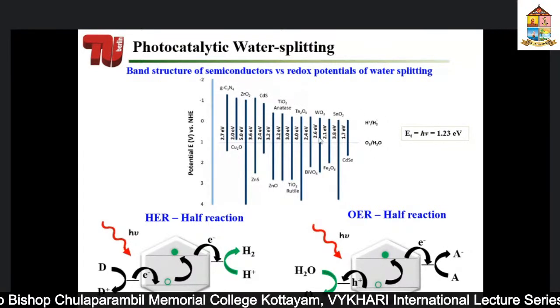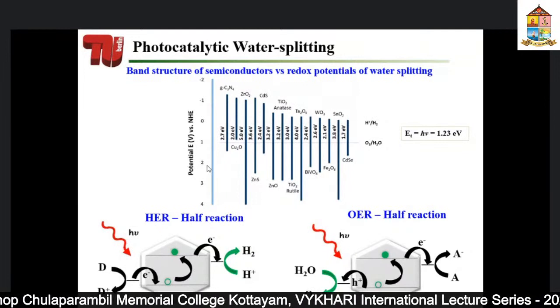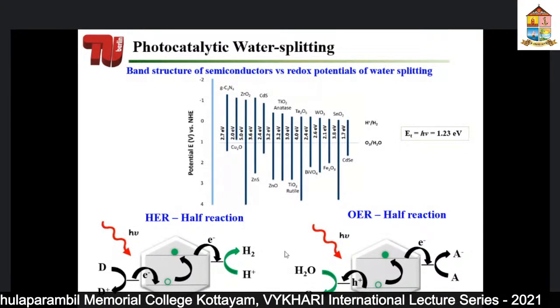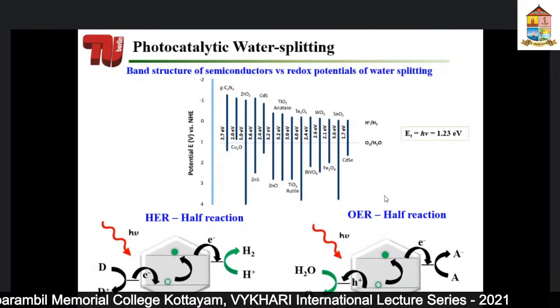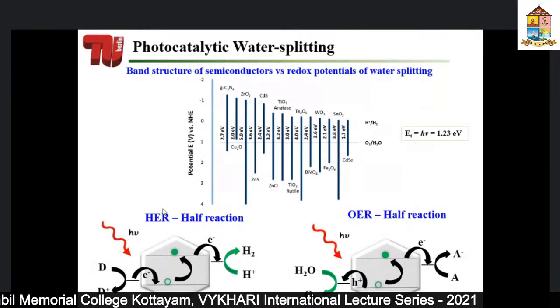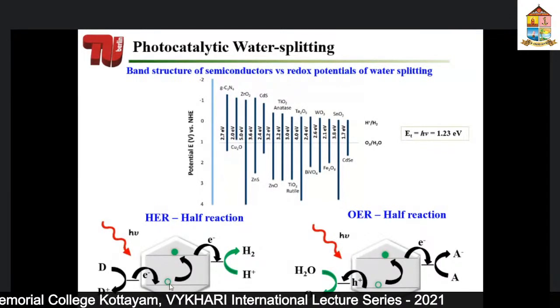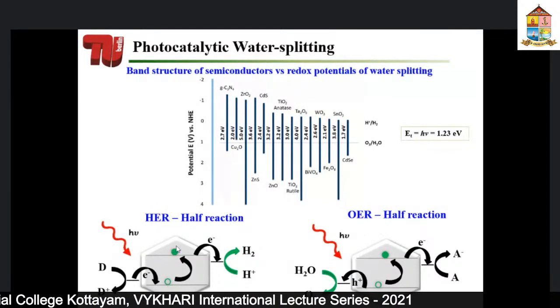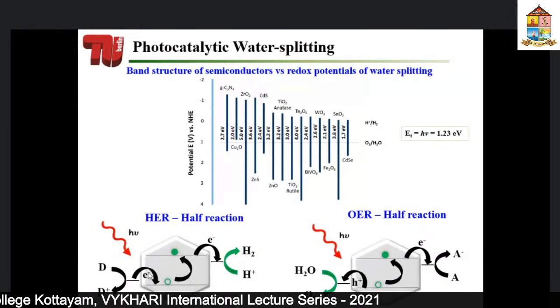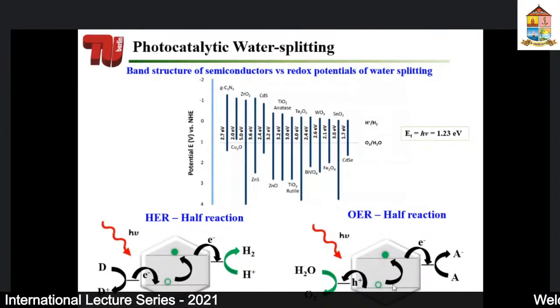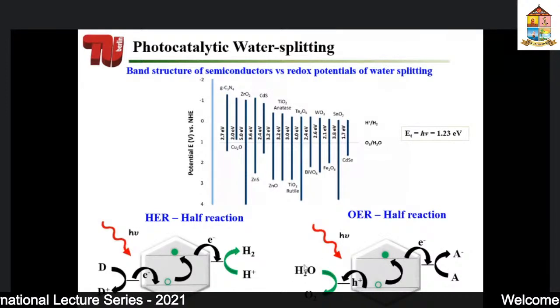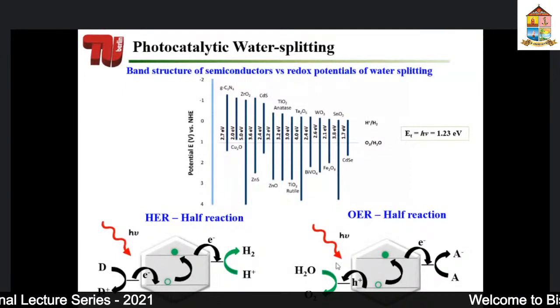What one could do is make a half reaction. That means you can produce hydrogen, which is what we want, and also the oxygen evolution reaction, which is an important reaction to compensate for the other half reaction. How can we do that? You hop the electron from your valence band to the conduction band, and immediately you can quench the hole by a donor atom, which sacrifices the electron and quenches it. So you can use the electron to make only hydrogen, no oxygen. Similarly, you can do the other way around. You can take an acceptor molecule, take the electron immediately, and use the hole to produce oxygen. This is very simple. So you can do this in both ways.